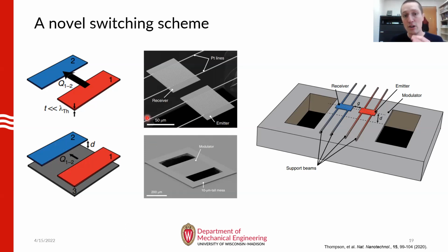Okay, so in the center here, you can see electron micrographs of the emitter and the receiver I used in this experiment, as well as the third nanomembrane below, which I call the modulator here. So in this case, all three nanomembranes are comprised of silicon nitride, and they're 500 nanometers thick. So under high vacuum conditions, I could then precisely align these three membranes in the configuration that you see here, and then adjust that vertical offset D with the piezo actuator.